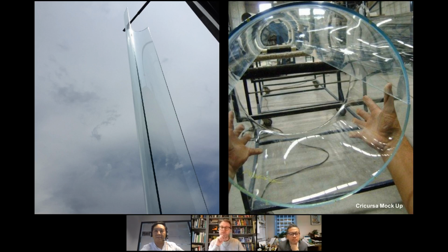Another really important part of this is the tricky bit of laminating, or curving, should I say, a 180-degree piece of glass, is that the last 25 to 30 millimeters of the curve, the sort of tangent, no longer remains fully curved, because the way in which glass curves, it uses its own weight to curve around the mold, and therefore as you get to the end, there isn't any other glass to pull that piece of glass adjacent to the mold itself. So you get a slight flare, and controlling that is super important.